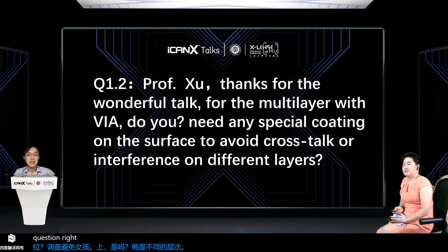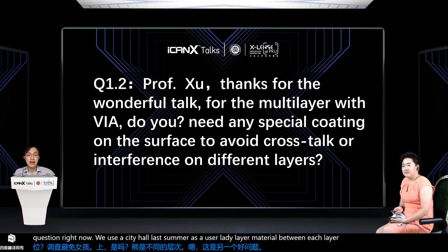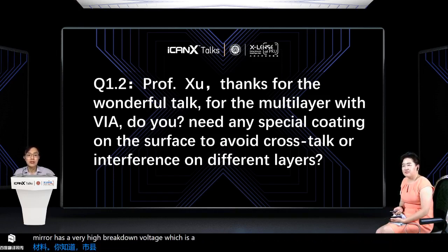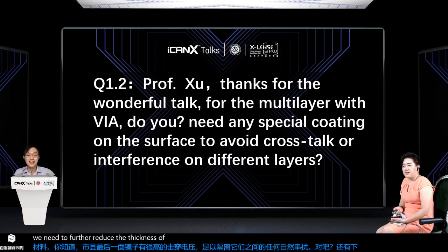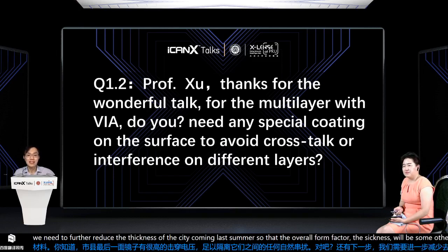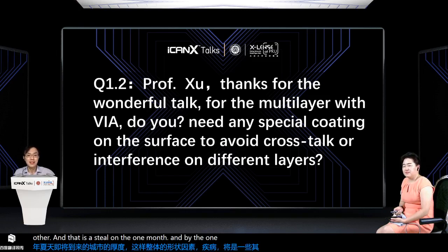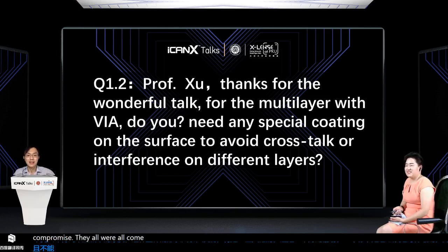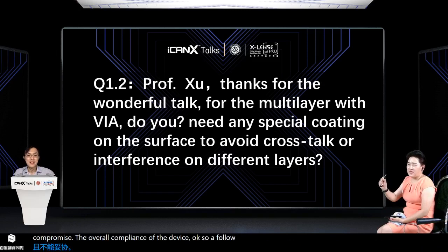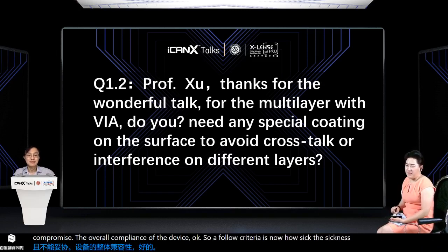Right now, we use a silicone elastomer as the insulating layer material between each layer. And as you know, silicone elastomer has a very high breakdown voltage, which is sufficient to isolate any electrical crosstalk between them. As a next step, we need to further reduce the thickness of this silicone elastomer so that the overall form factor, the thickness, will be smaller. That is still under development. But one criterion is that it has to be stretchable, so that it does not compromise the overall compliance of the device.